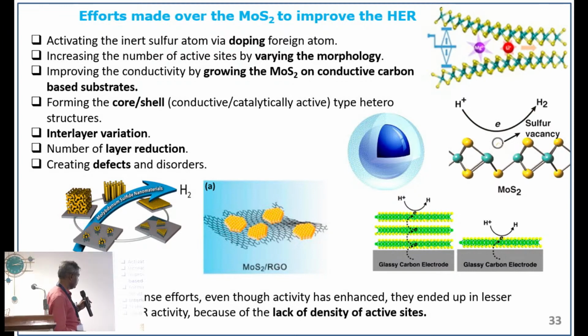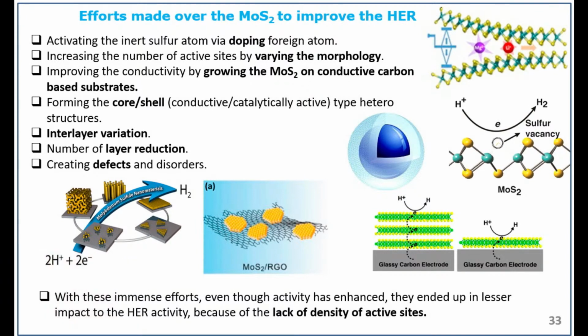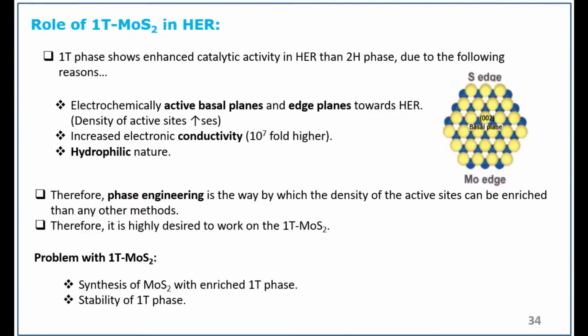Similarly, creating defects over the surfaces is also possible, and they are also active for HER. But the problem is with these improvements, even though the activity has been enhanced, they end up with a lesser impact on the HER activity because of the lack of density of active sites, because the number of active sites per unit volume is very low. So they cannot reach a particular level. So that is the role of 1T in MoS2.